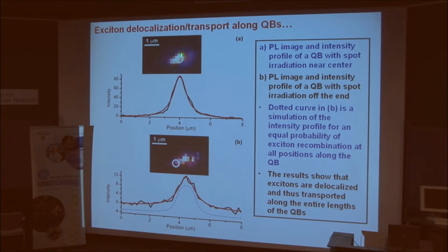However, Ginny then moved the spot off the end of the belt so it was just overlapping with one end. And that's this experiment here. And then she again plotted the intensity profile over the length of the belt. And again, the maximum intensity is right in the middle of the belt. And then we did a simulation as to what should the intensity profile be if there's an equal probability of emission everywhere along the length of the belt. And that gave us this, which is to say that no matter where the exciton is generated, it has an equal probability of recombining and re-emitting at any point along the length of the belt. That is to say, excitons are effectively delocalized along the entire axial dimension of the belts.